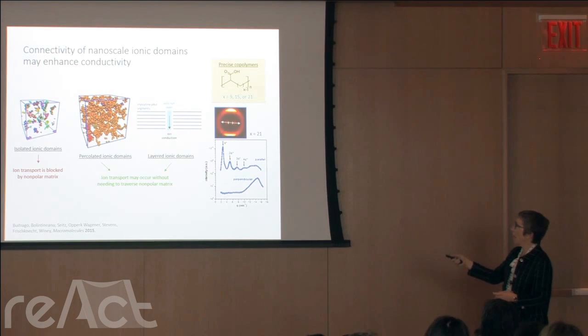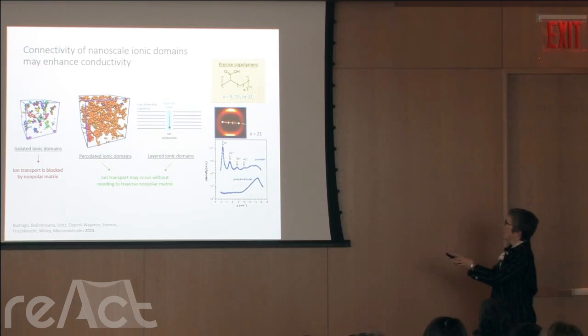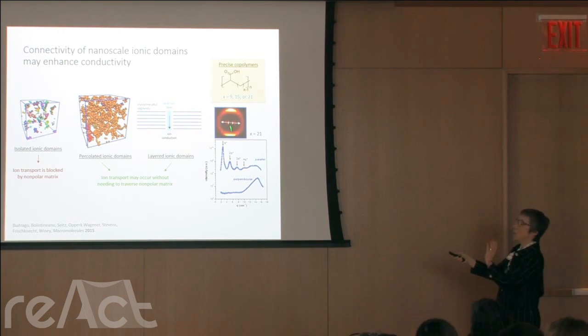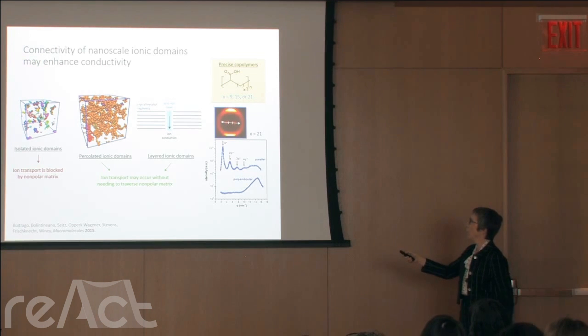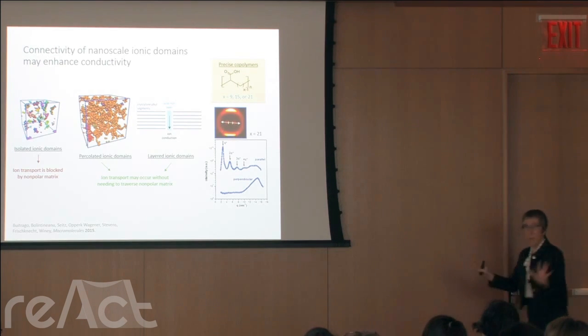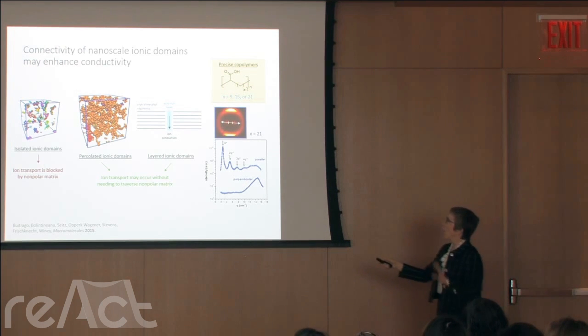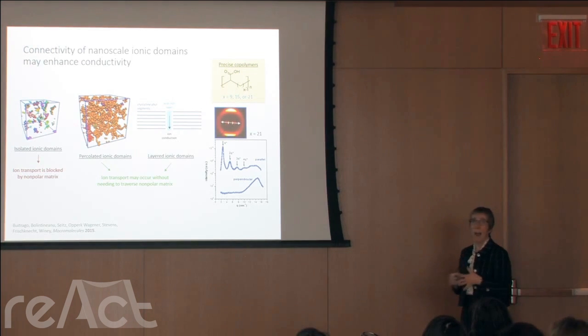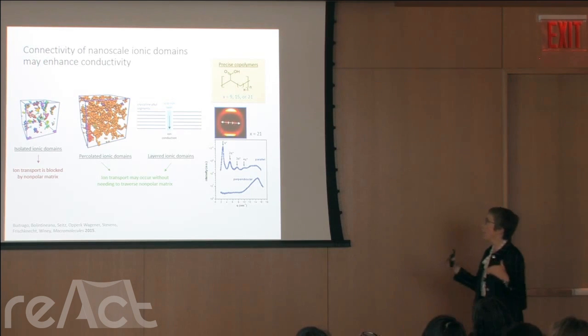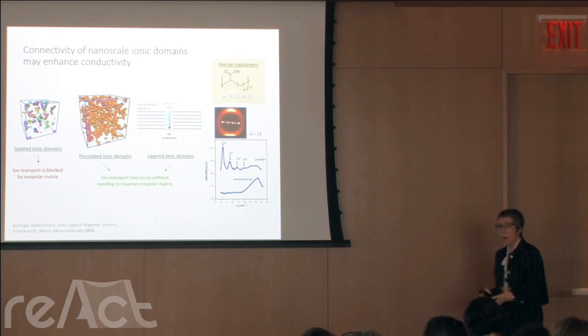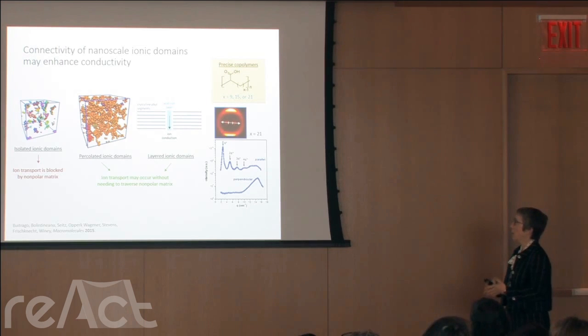Another possibility would be these semi-crystalline materials that we found, where there is a crystalline domain separated by these layers of acid groups. And so when we stretch in this direction, we can see there's two sets of scattering peaks. There's these low angle peaks and these high angle peaks. And that perpendicular orientation of those two scattering peaks indicates that we have polymer chains running this way and layers running this way. And these higher order peaks tell us that we really have layers. But the take-home message is both percolated structures and layered structures, ionic aggregates that form these two shapes, have more connectivity. The ions are more connected to one another, and that could facilitate ion transport. And now it's a matter of designing the molecules that will allow us to evaluate that.